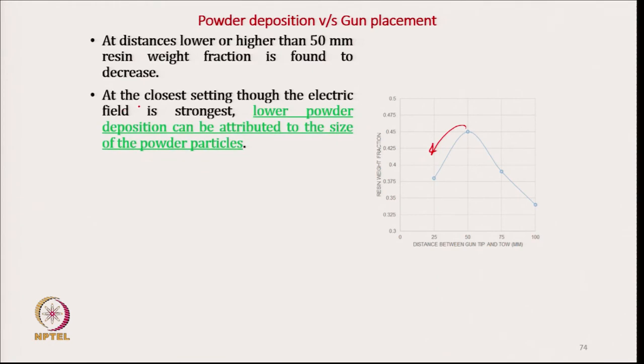At the closest setting, though the electric field is strongest, the lower powder deposition can be attributed to the size of the particle. At that lower distance, the size of the particle is a little bit larger, so it has very high inertia. With that inertia, if it strikes the tow, it will immediately bounce back or will not stick to the surface, it will reflect, because at lower distance the inertia is very high.